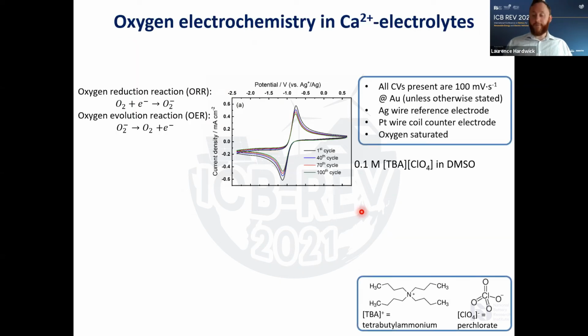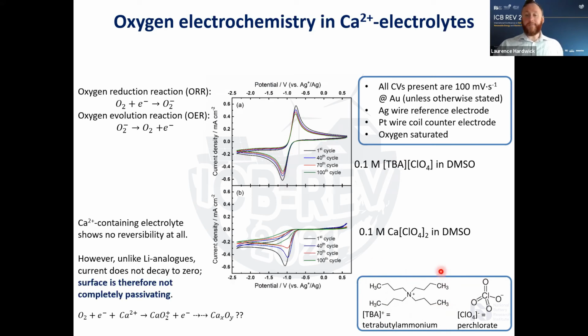We use spectroscopy to characterize what is happening. So typically when you have this composition of tetrabutyl ammonium, this ammonium salt with these long butyl chains here, we get quite reversible cyclic voltammograms. Then if we add a calcium salt, so we've replaced our tetrabutyl ammonium with calcium, you see that it becomes irreversible. We can't oxidize back any of these components that are formed. However, what we noticed, and it is very important to notice, is that this does keep cycling. Whatever's forming on the surface when we have calcium is not completely passivating. So the electrode doesn't become passivated, and so we can still have some reaction taking place.